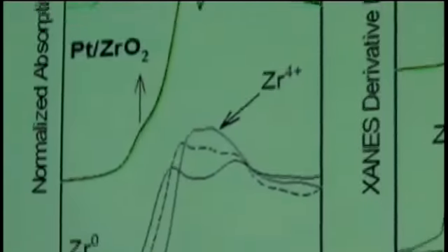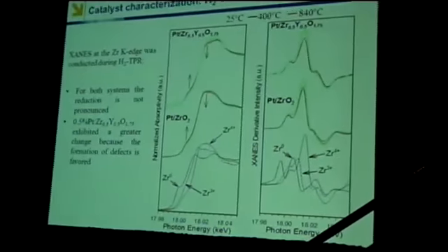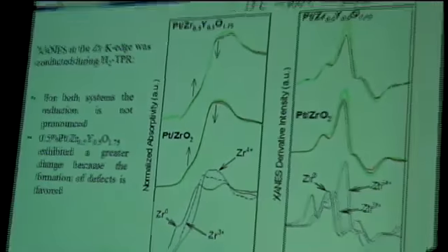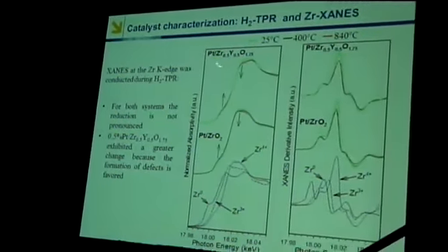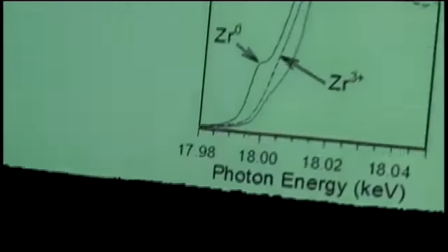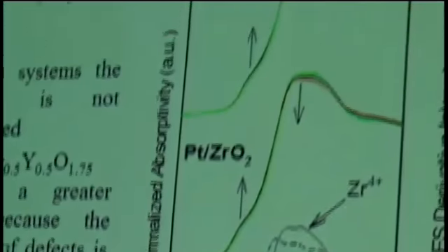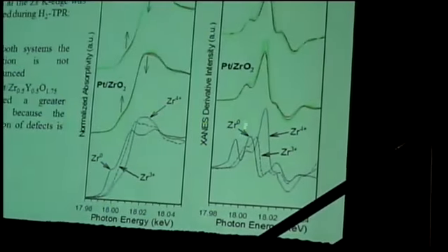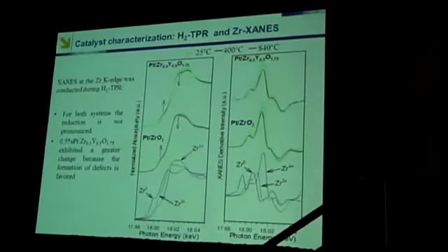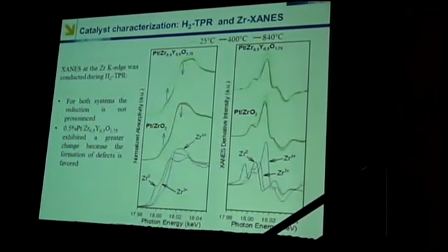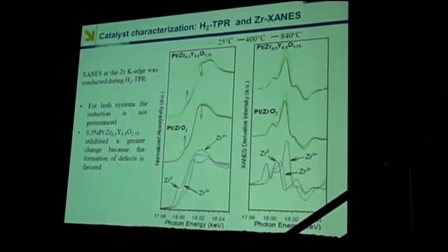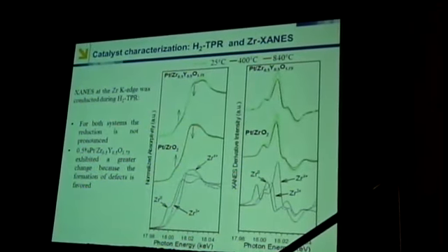We also looked at XANES for the zirconium K-edge, for the undoped and the 50% yttrium-doped catalyst. And unlike ceria, where you see very significant changes in XANES, the extent of reduction is much more limited for zirconia. But we do see a more significant change in the white line for the yttrium-doped catalyst, suggesting that the reduction is more facile.